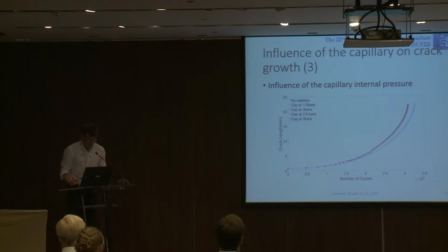But before we can be totally happy, remember that I explained in the beginning that the working principle is based on the fact that inside your capillary you have another pressure than the atmosphere. You can be under vacuum or under a high pressure. And again, the question arises whether this high internal capillary pressure has an influence on the crack propagation life. To do that, we have taken the same model, this time only with a capillary of 2 millimeter diameter, and we have applied different internal capillary pressures.